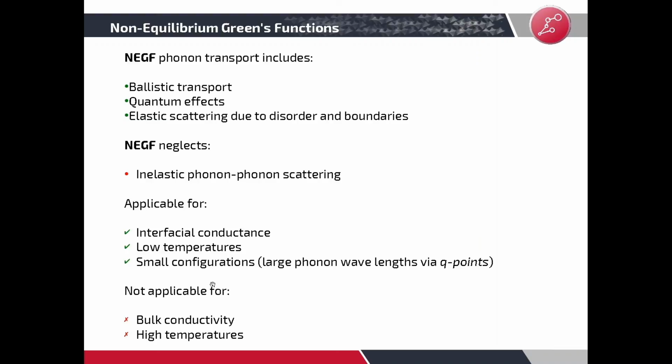On the other hand, NEGF phonon transport is not applicable to calculate the bulk conductivity, because one of the main dominating contributions to the resistance in bulk conductivity is inelastic phonon-phonon scattering, and that is not accounted for by this technique. And also due to the lack of anharmonic effects, we would expect some more severe deviations, especially at high temperatures.